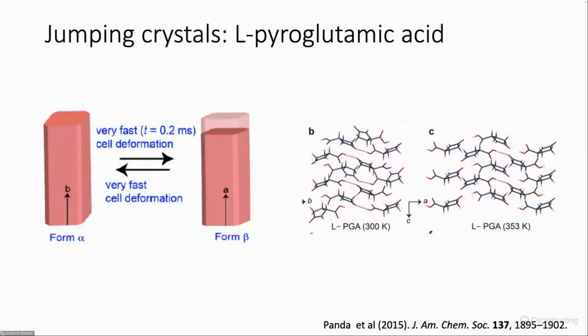What is going on here? Well, it's related to a very abrupt change in crystal shape. So there's a very abrupt change in the crystal packing as we go above this phase transformation, and we can compare the two crystal lattices here. Actually, they are not that different. It's very small changes, but they occur very abruptly, and that leads to this very large energy output as we heat the system, and this gives rise to a sort of spring tendency where the crystal is moving.